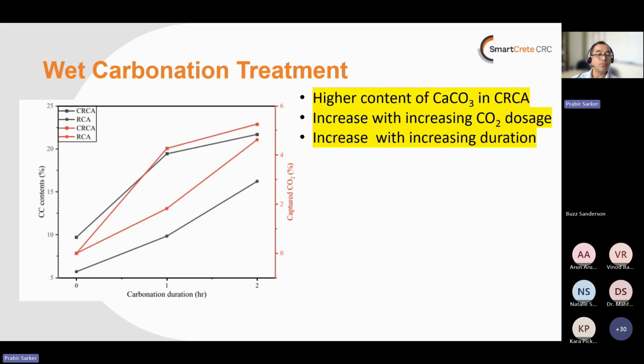So we can see the effect on the deposition of calcium carbonate here. The vertical axis on the left hand side is the calcium carbonate content, calcite content. The horizontal axis is the duration of carbonation, and the vertical axis on the right hand side is the captured carbon dioxide, which can be related to carbon dioxide sequestration. So you can see as the carbonation duration increased, the calcite content produced on the aggregate increased in both types of recycled aggregate, and also the captured carbon dioxide increased.